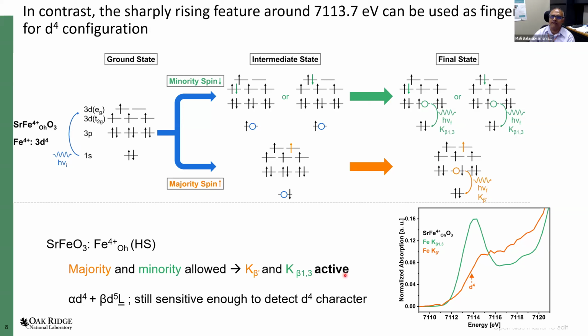So far, most of the discussion that I have done is assuming that the ground state is purely ionic. However, in these systems, particularly for the Fe4+, the ground state is actually very covalent in nature. So one can represent the ground state using alpha times D4 and beta times D5 with an L bar, where this L bar corresponds to a hole on the oxygen. Even under these circumstances, as you can see here, we can still faithfully detect D4 character using X-ray emission methods. So we believe that looking at this using resonant X-ray emission gives us a fingerprint for seeing if there is any D4 character in the ground state.